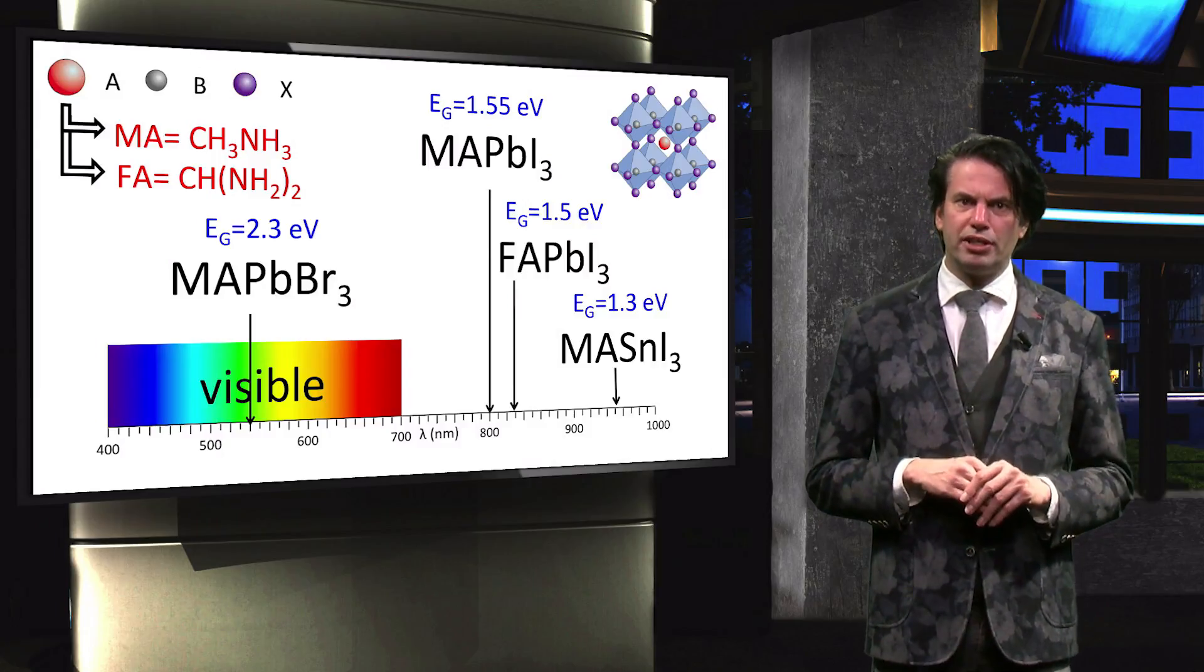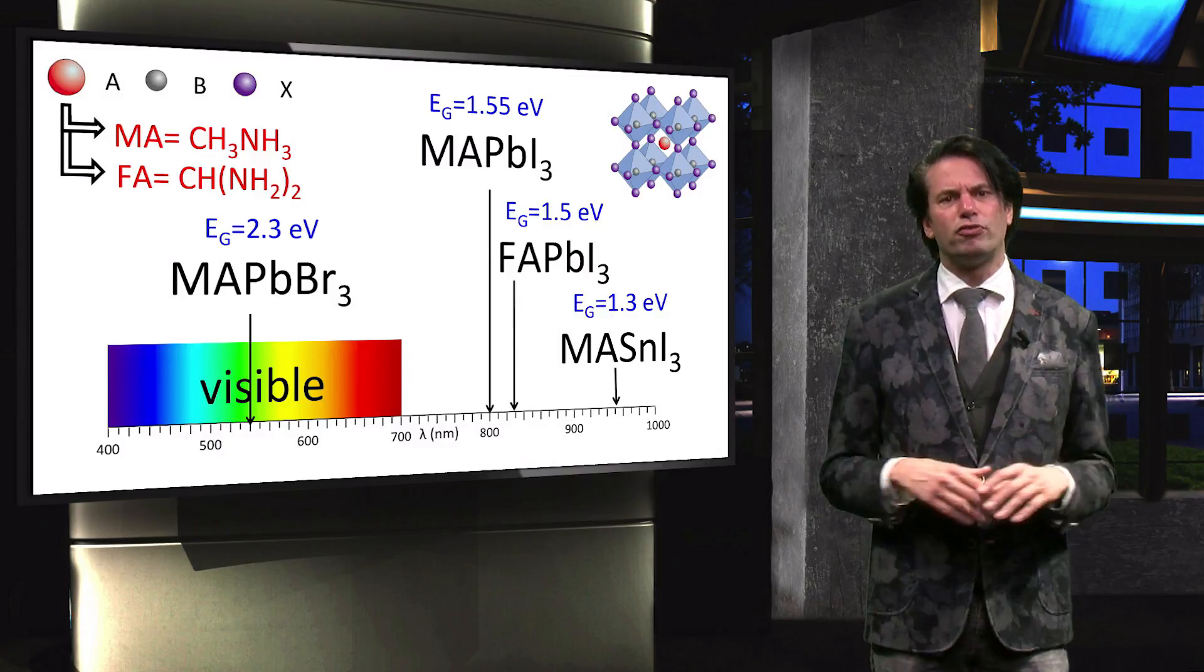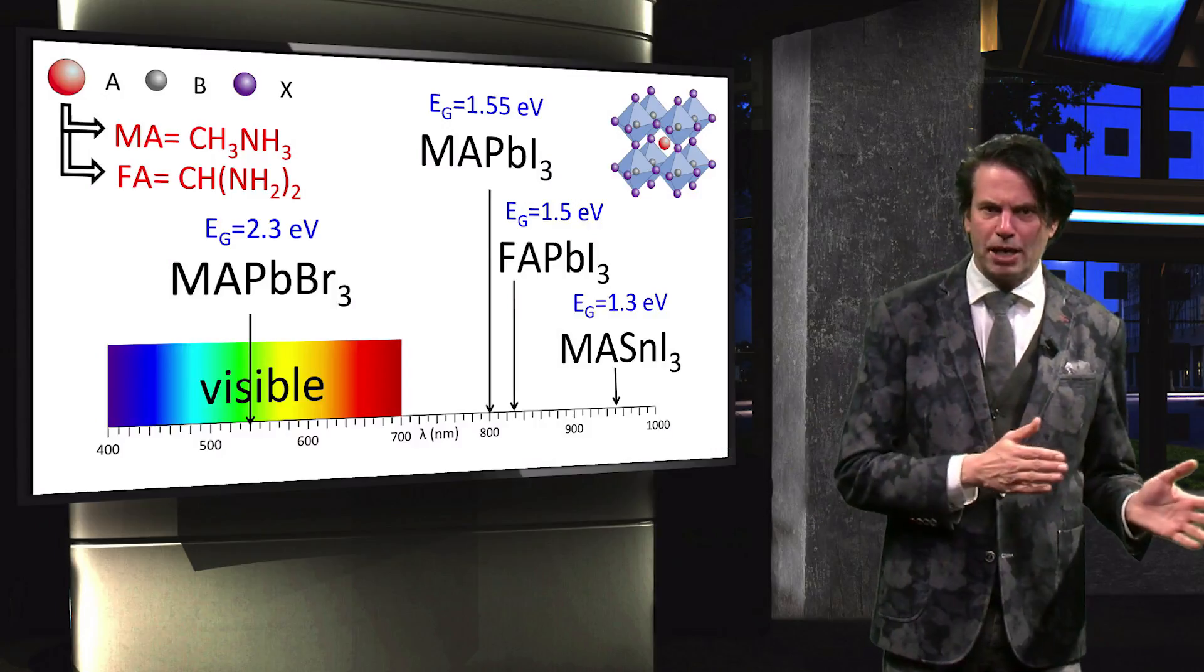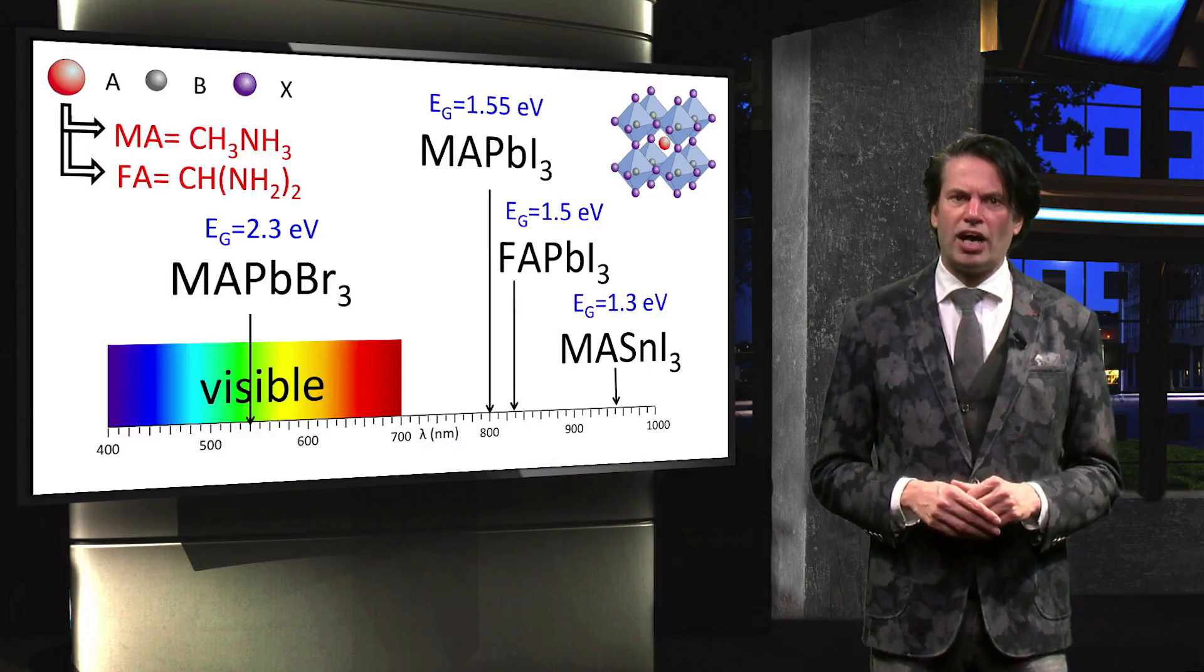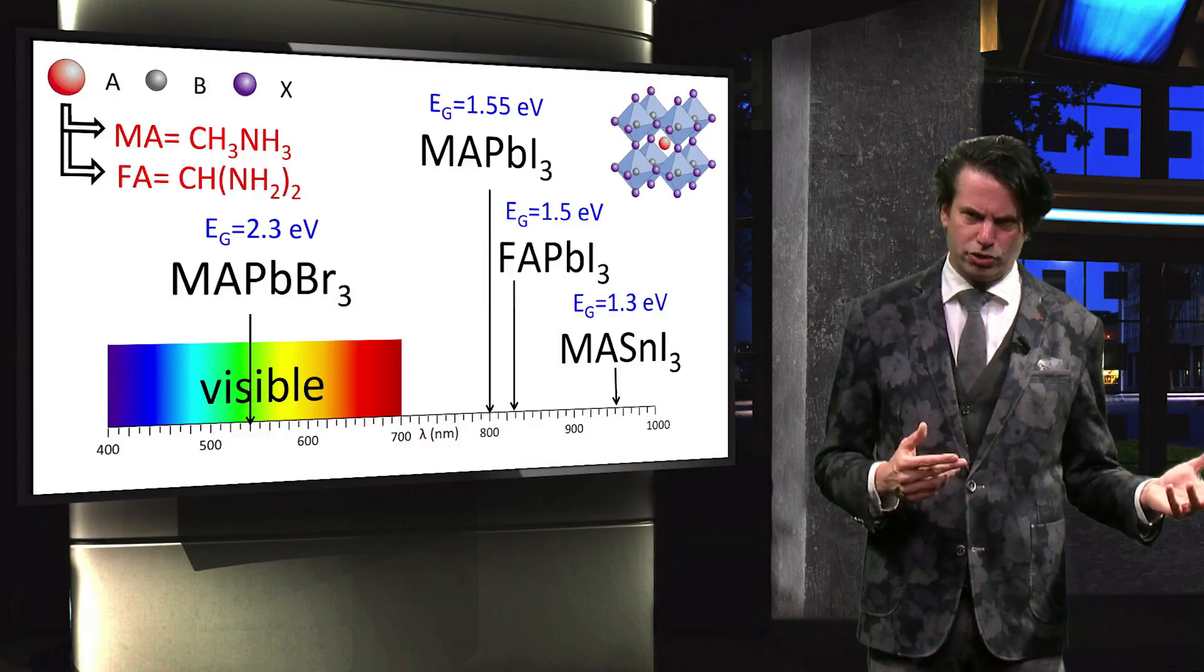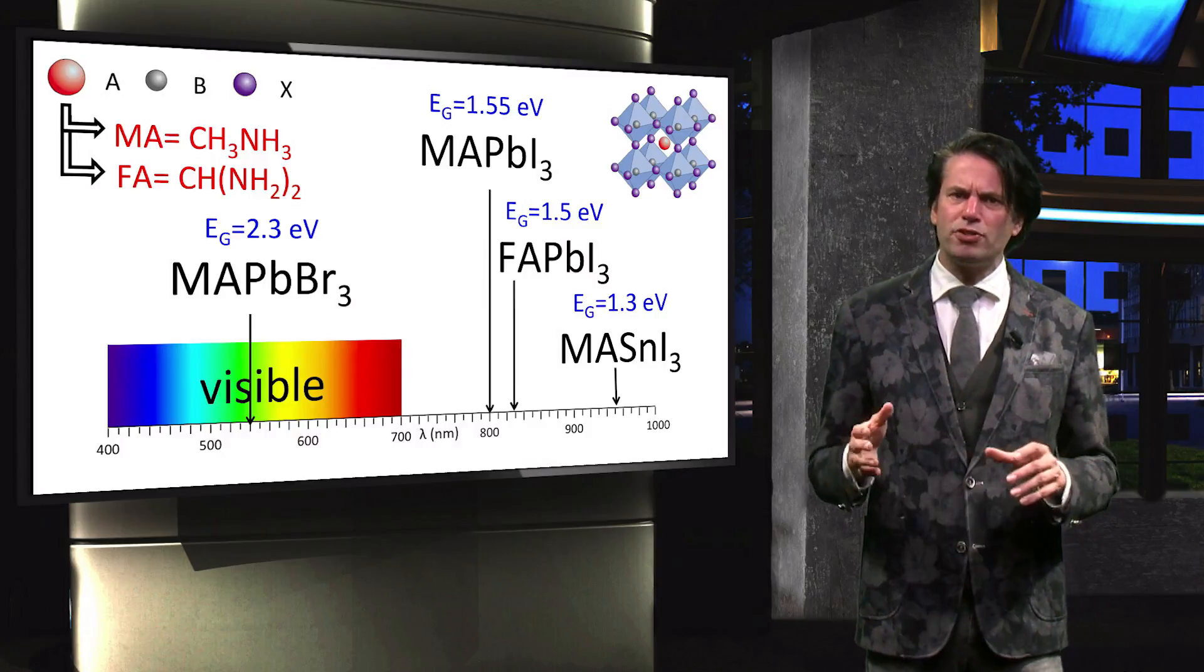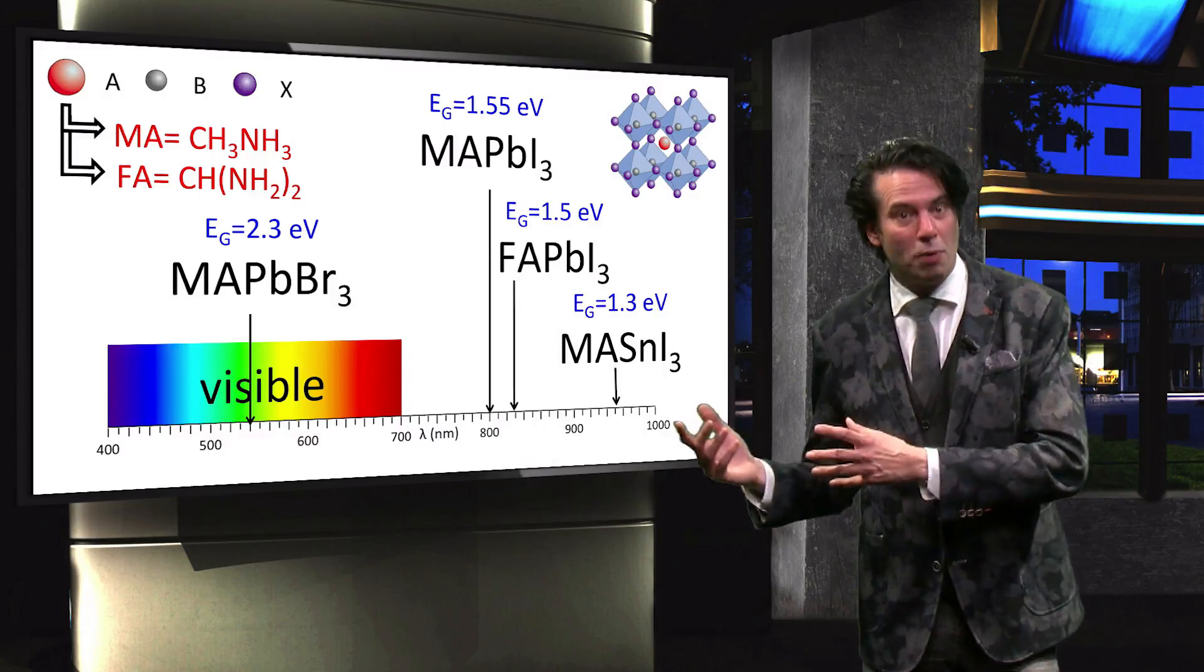Its value is in the order of 1.5 eV, which corresponds to the wavelength of 827 nm. Of course, bandgaps can be tuned using mixtures of these different halide perovskites. For instance, for hybrid tandem applications, higher bandgaps than that of the methyl ammonium lead iodide are required. Such applications require halide perovskites material based on a mixture of methyl ammonium lead iodide and methyl ammonium lead bromide.